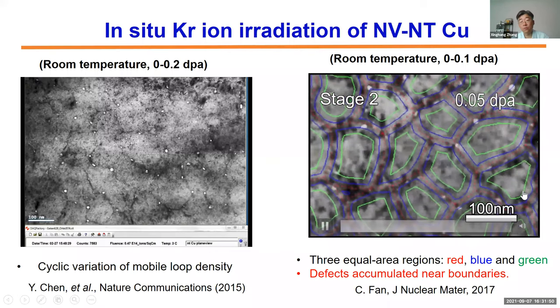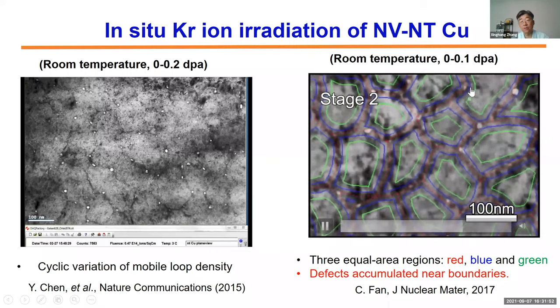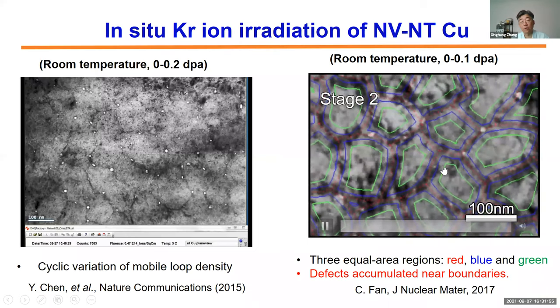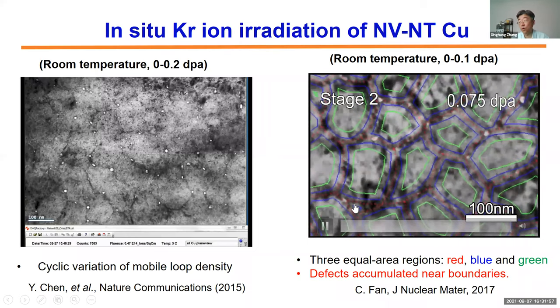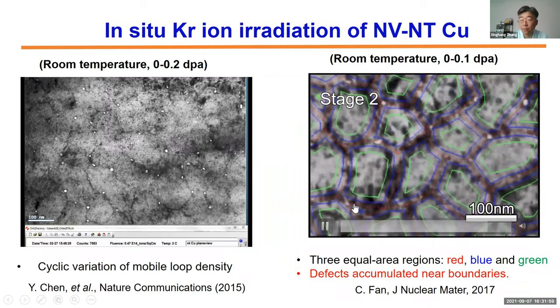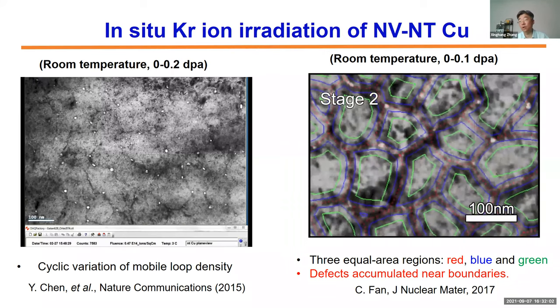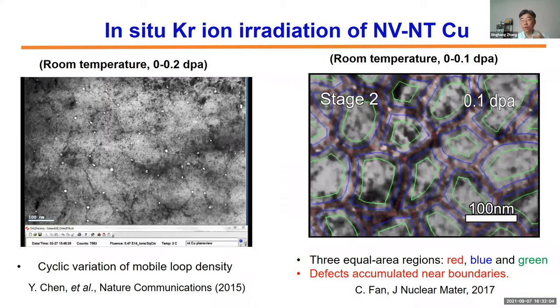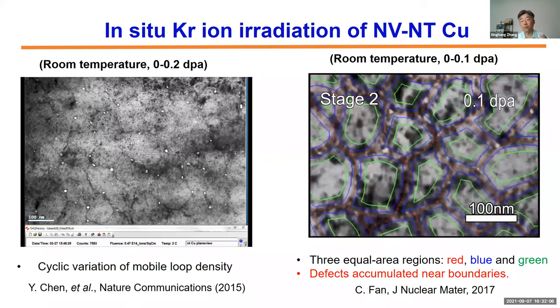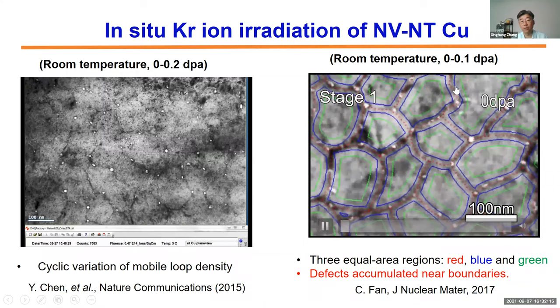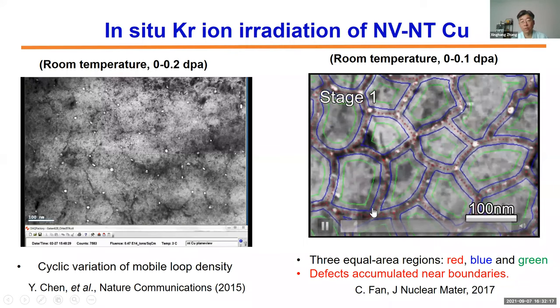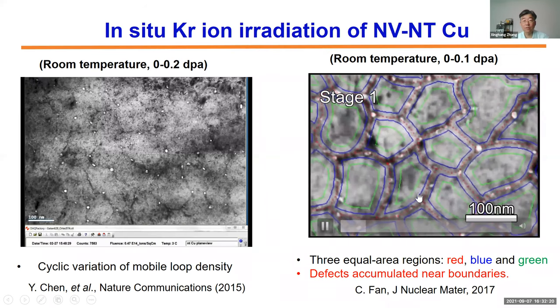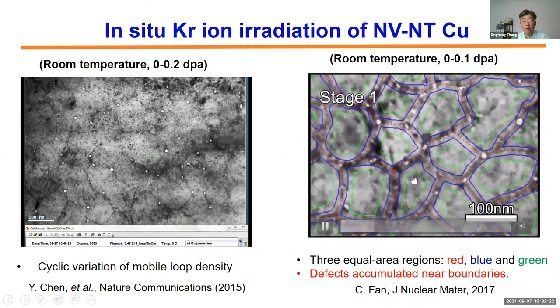One thing you notice, which is quite bizarre, is that these defects are surrounding twin boundaries. And we all know in the metallic material community, if grain boundaries are good defect sinks, then very often you have seen reports of a void-denuded zone, or defect-denuded zone, near the grain boundaries. But at least in the early stage of radiation, we saw a defect-populated zone right at the grain boundaries in this case. So that is nano void, nano twin copper.